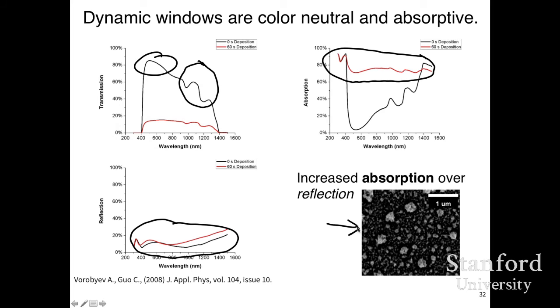But having this nanostructured metal is causing the light to get very heavily scattered, and then we're probably exciting a lot of plasmonic resonances in the nanoparticles that's leading to strong absorption. But yeah, there is some debate. Some think it would be great to reflect the light, and that would keep the window cool, and it would just reject the heat. But a lot of people we've talked to actually prefer the absorption and the black color, and point out that you really don't want your window to look like a mirror.